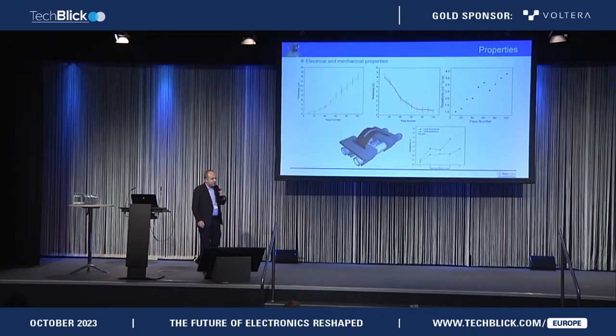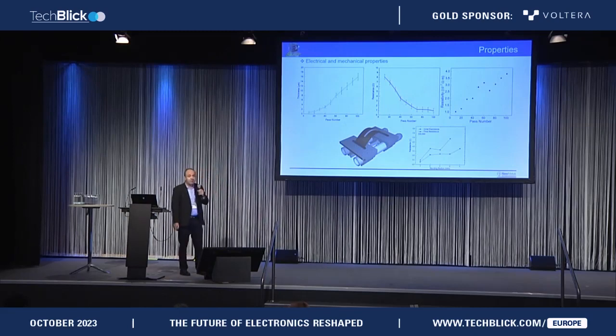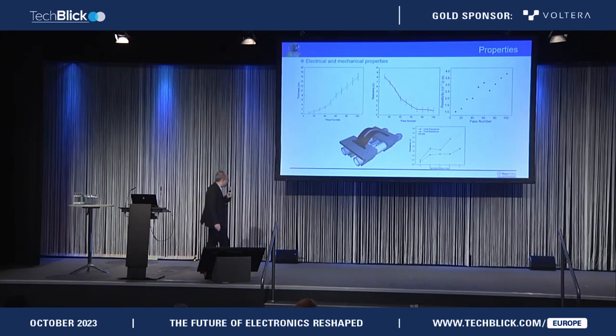And of course, just to show that this technology is reliable, we do a lot of measurements and property investigation. For example, we study the thickness variation as a function of the number of passes or printed layers. This is a layer-by-layer process. You can print even one layer, which is going to give you about 100 nanometers, or you can repeat it, go up to a few microns as you wish.